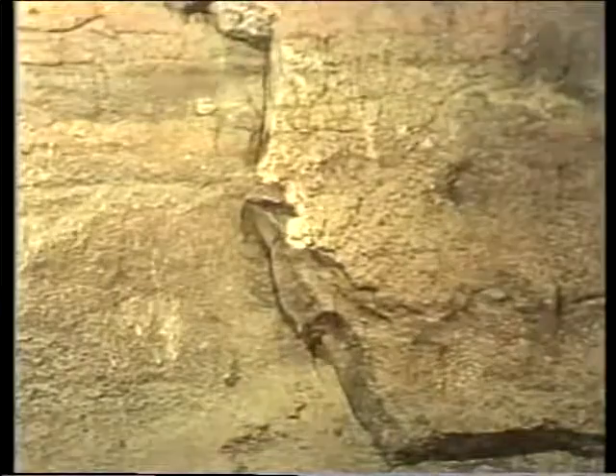Slag attack is the chemical reaction of ash and refractory. Slag attack erodes refractory, reducing its thickness. It melts the refractory and causes it to run off. Slag attack may also cause refractory to become soft and crumbly. In some cases, slag attack will produce a glassy surface.